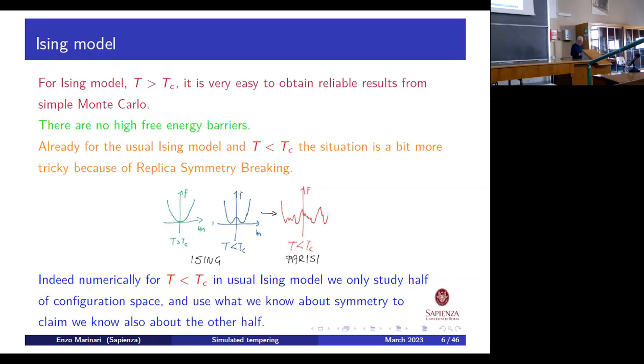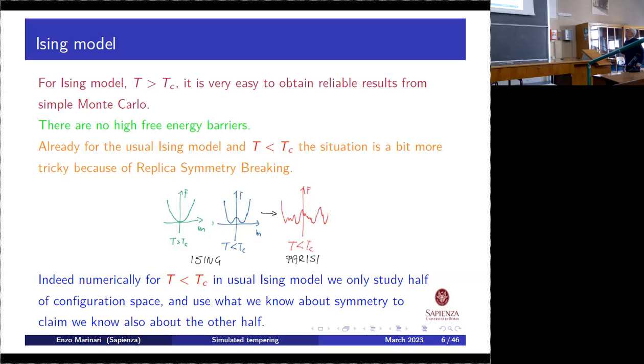Now, let us think of the simple Ising model. Spins that are plus or minus 1, ferromagnetic interaction with the first neighbors, right? Something very simple. And for example, now, if you have large temperatures, it's very easy to obtain reliable results for expectation values of energy, for example, from simple Monte Carlo. This is because there are no high energy barriers. But I want you to notice that already when you go in the broken phase of the Ising model, the situation is a bit more complicated than what you would think.